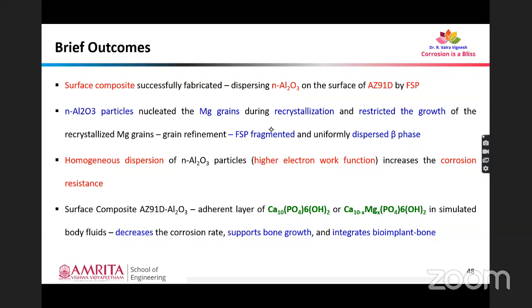Added to that, the surface composites had an adherent layer of calcium magnesium phosphate or calcium hydroxyapatite in simulated body fluids that resulted in decreased corrosion rate. And previous studies have also confirmed that if there is formation of such compounds, that will enhance osteoconductivity and it will support bone growth. So from this, we can conclude that magnesium alloy that is reinforced with nanophase alumina is going to be an effective biodegradable implant.